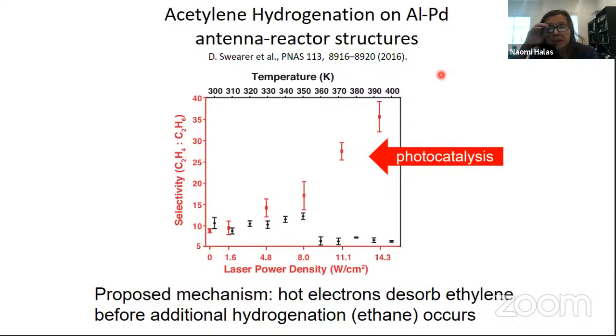So let me show you here. This is a contrast between taking that same aluminum palladium antenna reactor that I showed you and doing hydrogenation of acetylene. The black points are the reaction in the dark, and they correspond to temperature, which is up on the top of the graph. So there's no light at all. We're just running the thermal reaction. No matter what the temperature across this range, what we're looking at on the y-axis is the selectivity, or that ratio between ethylene and ethane. So the higher this number, the more selectivity we would have for ethylene. If we look at the thermal reaction, the best we can do is about 10 to 1. But it tends to be relatively low.